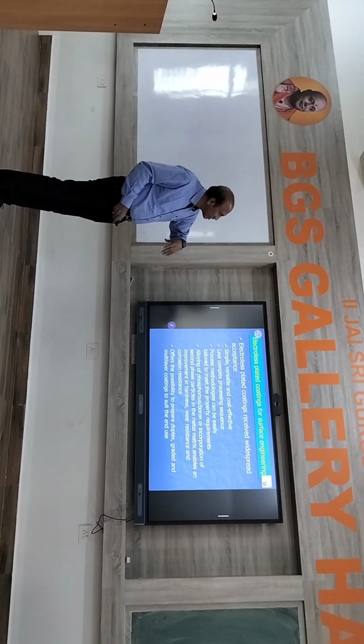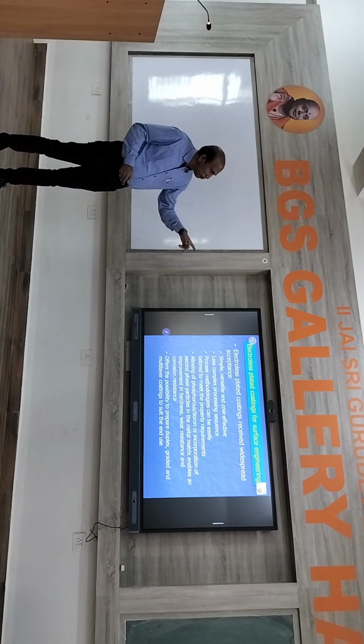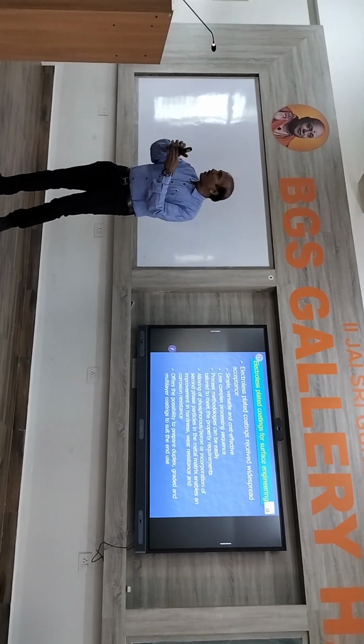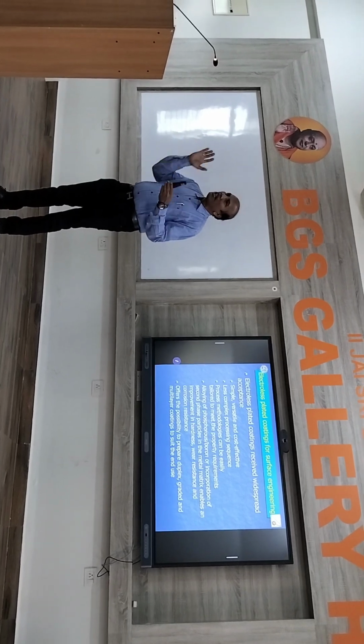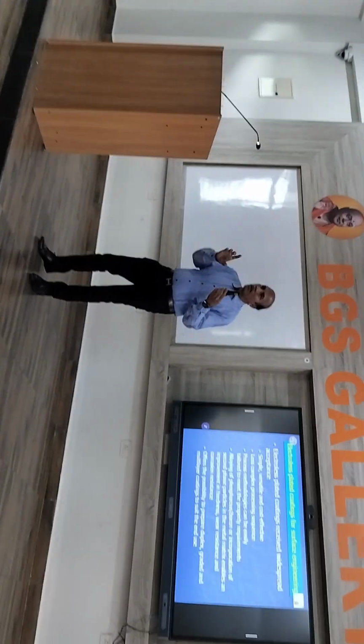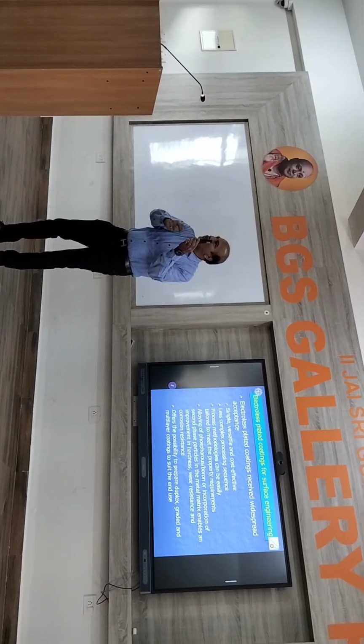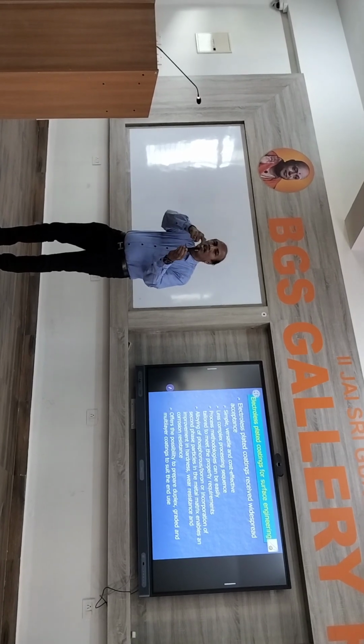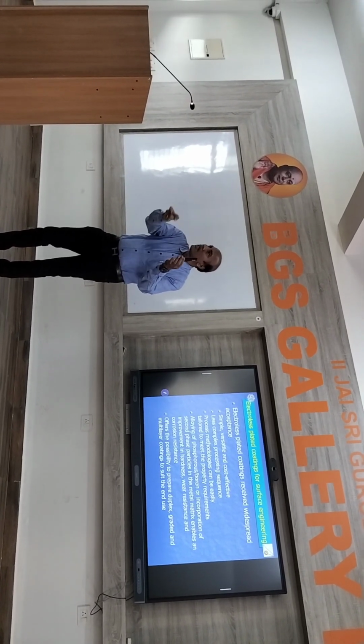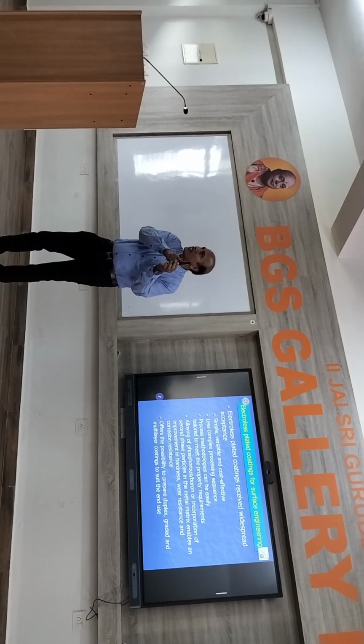Okay? Let me go to electroless plated coatings for surface engineering. As I told you, it is simple, versatile and cost effective. For example, if a very complex shape is there, by electrodeposition, what will happen? It depends on the current density lines. Because of that, probably I want 25 microns, a uniform thickness on this part. What will I end up with? I may get some 100 microns here because current density lines are much higher compared to this center portion. So there is a non-uniformity there.